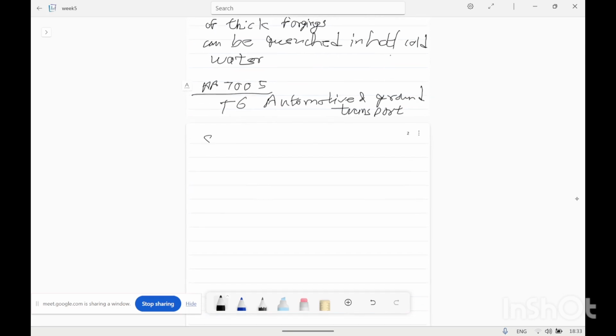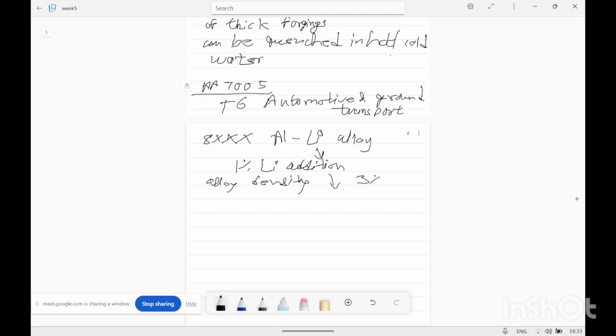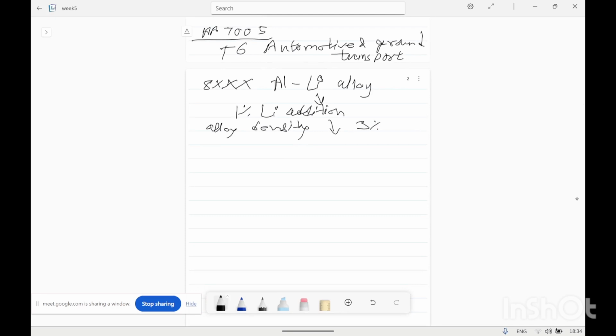So next are the 8 series alloys, which are aluminium lithium alloys. Aluminium lithium alloys have some special properties, such as lithium has lower density. By addition of 1% lithium in aluminium, the alloy density decreases by 3%. The aluminum lithium alloys became popular in the 1980s and 1990s because of their light weight and high strength.